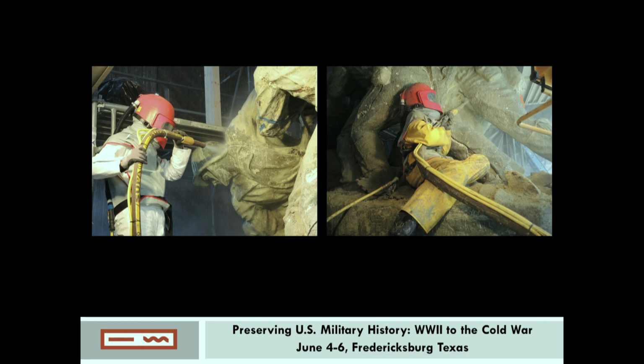This coating removal phase was done by wet blasting using recycled crushed glass. About 1.2 tonnes of fine glass media were used, and approximately 95% of the coating was removed. In some areas, such as deep recesses, undercuts, and in places where the coating was extremely thick, it had to be done mechanically afterwards because we didn't want to remove the surface of the concrete. We tested this on numerous pieces that were already removed from the sculpture so we could get the optimal distance, pressure, etc.